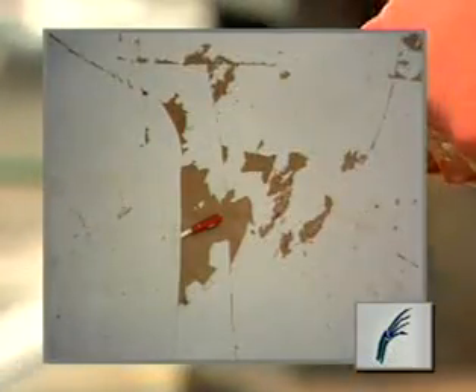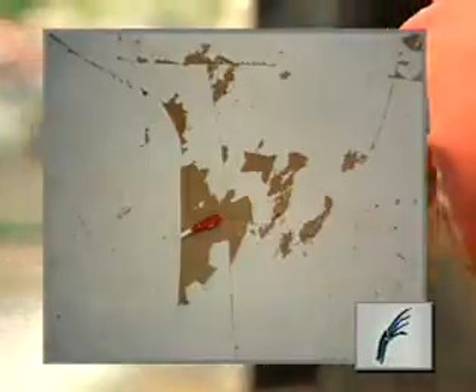95% of all paint detachment problems are caused by the presence of salt, moisture or oil contamination. So make certain you keep washing with sufficient fresh water until all traces of salt, dirt and oil are removed from the surface to be coated.